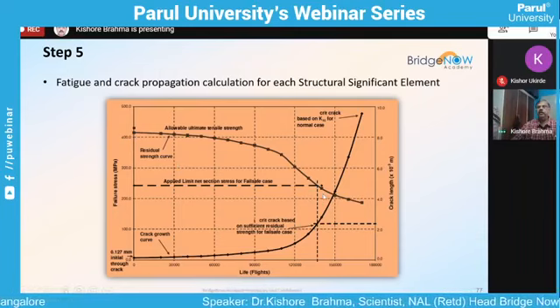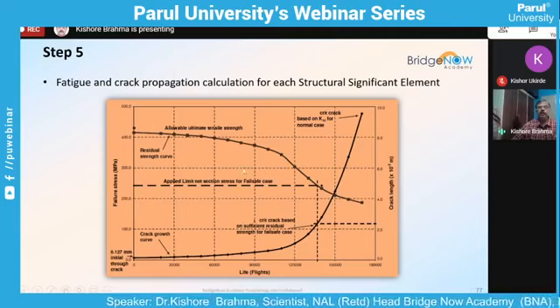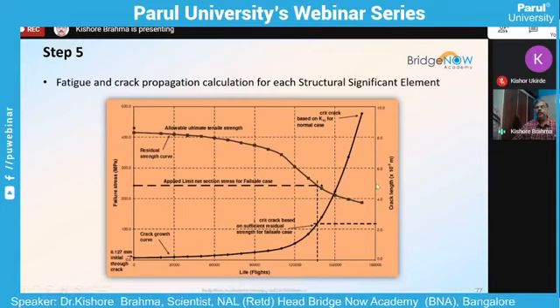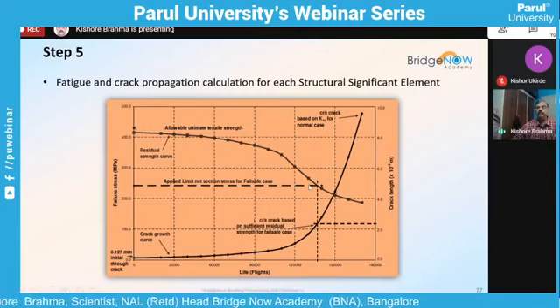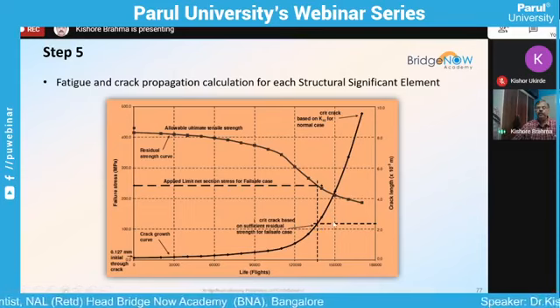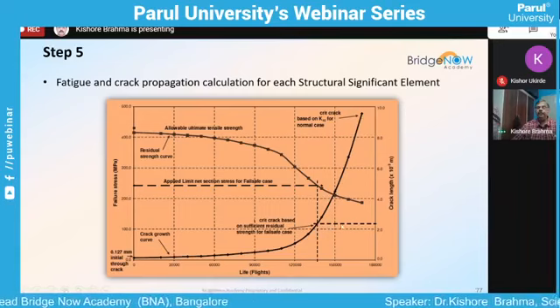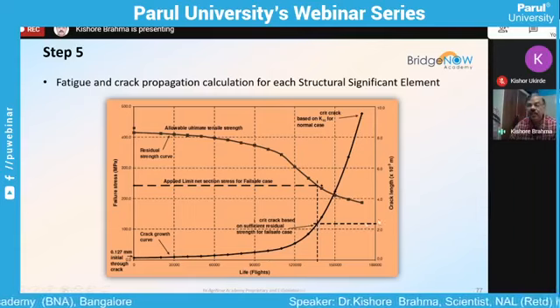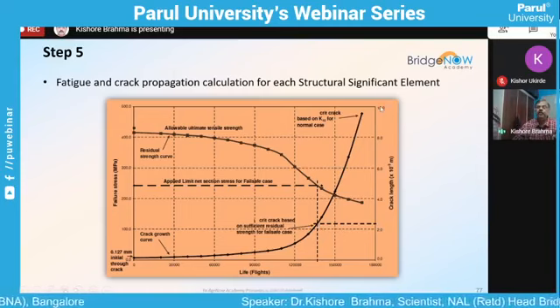But as per the regulatory authorities, the regulation for certification, your residual strength should not fall below the limit load. This is the lower limit load, which is derived from the static analysis. If you see that, it corresponds to 5 mm. The critical crack length is supposed to be 9 mm, but due to the regulatory airworthiness requirements, it is 5 mm. So only this much is available for your inspection interval, not from 5 mm to 9 mm. Starting from the detectable crack length, which is around 2.3 mm, it is not from 2.3 to 9 mm. It is from 2.3 to 5 mm. Within that, you have to arrive at the inspection interval.